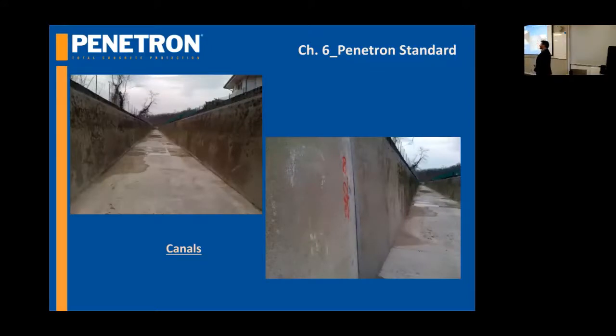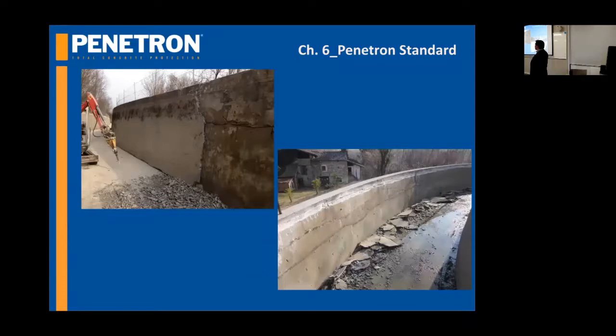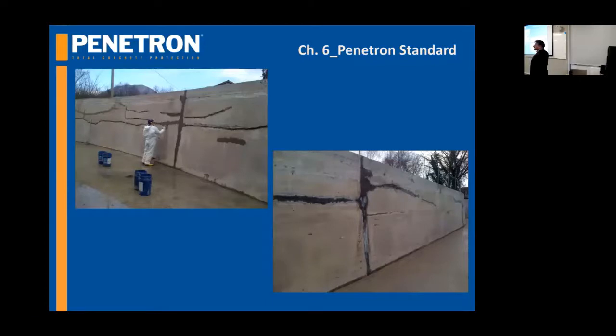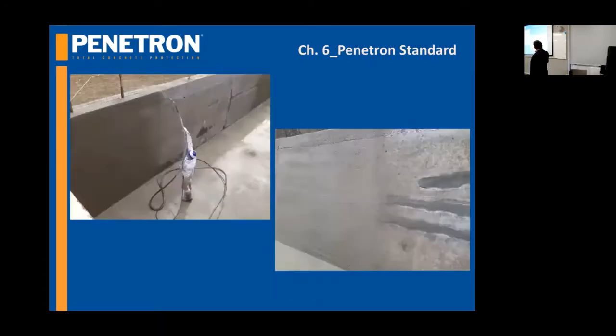Another application is for canals. In this case, the canals had an old, damaged coating. First thing, remove it, and we have to reach the original concrete. After that, all the cracks have been repaired, and the solution chosen was to use Penetron, not applied by brush, because it was too expensive in terms of time. So we decided to spray it with a machine that could do this.